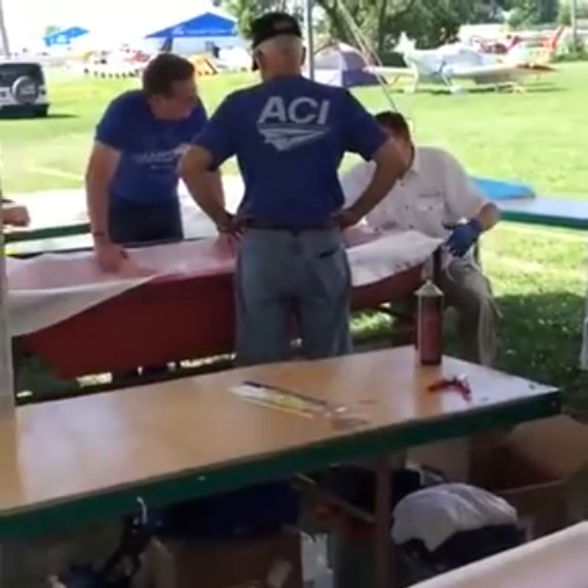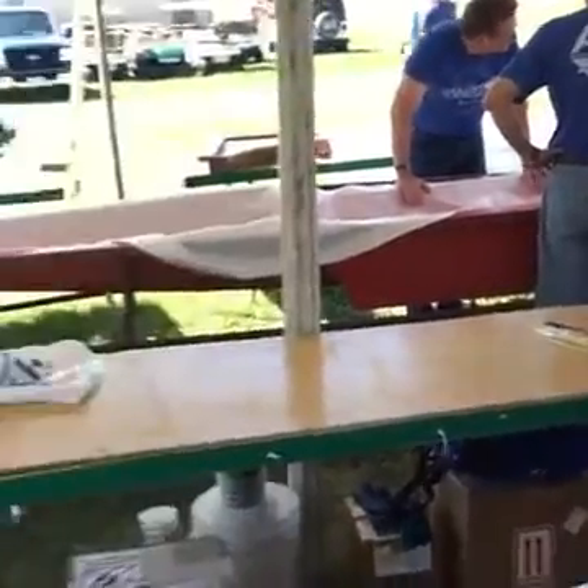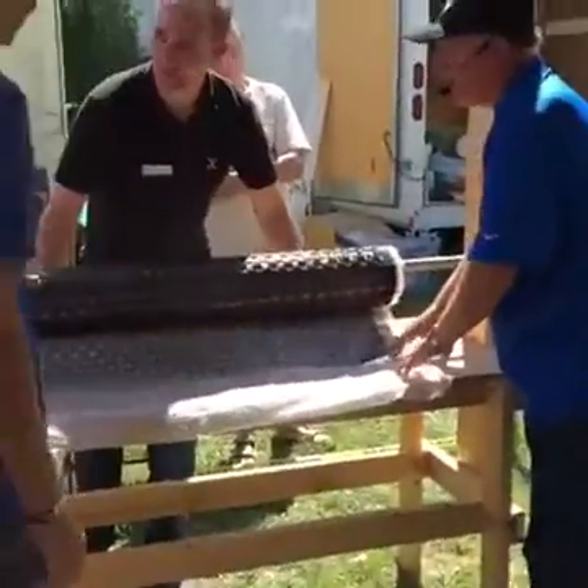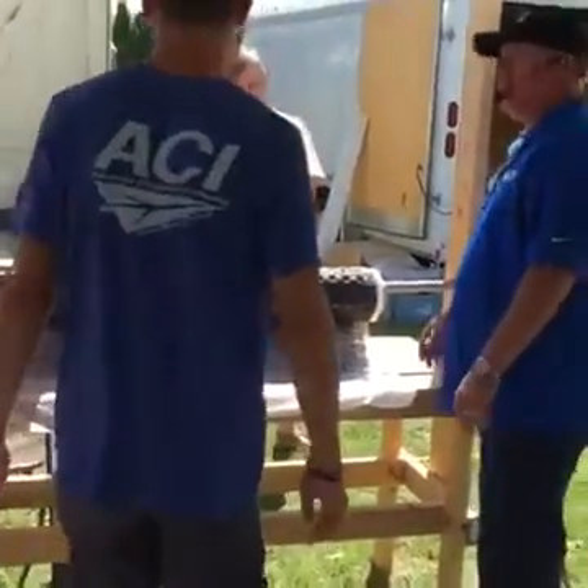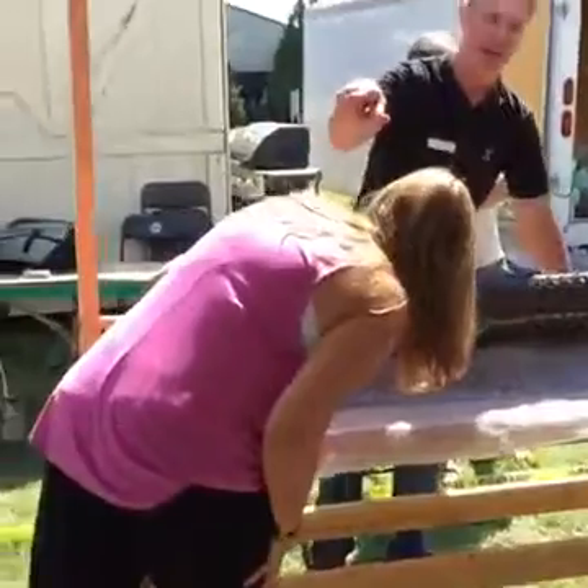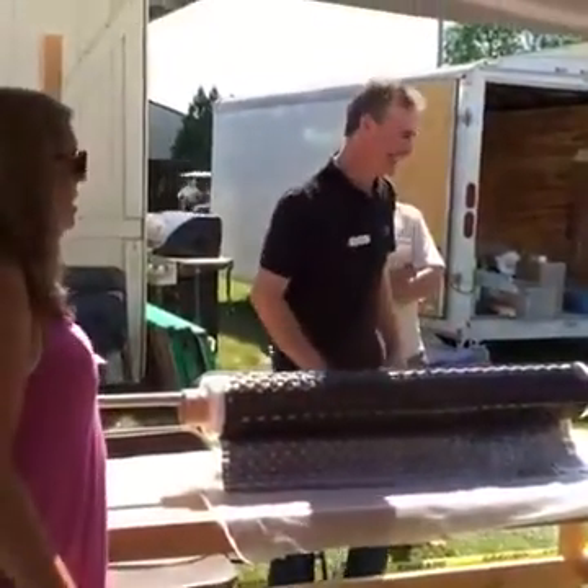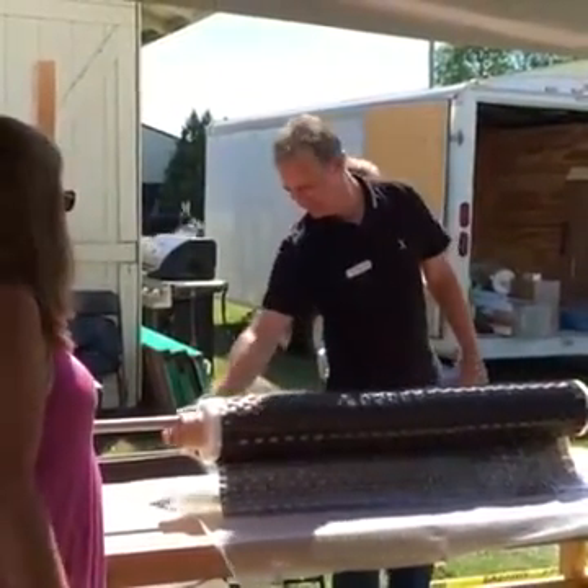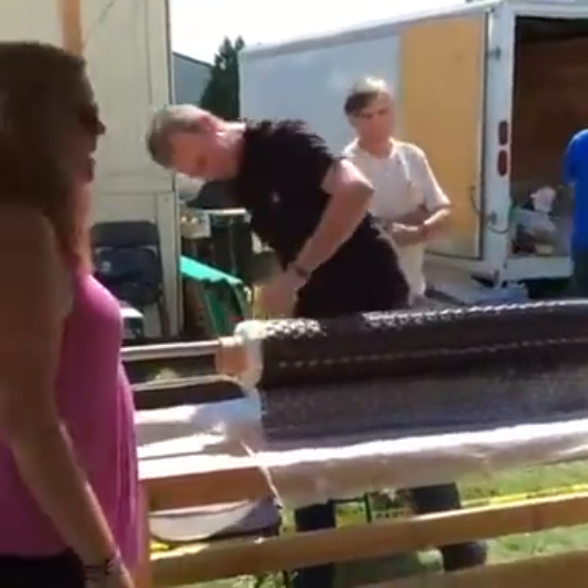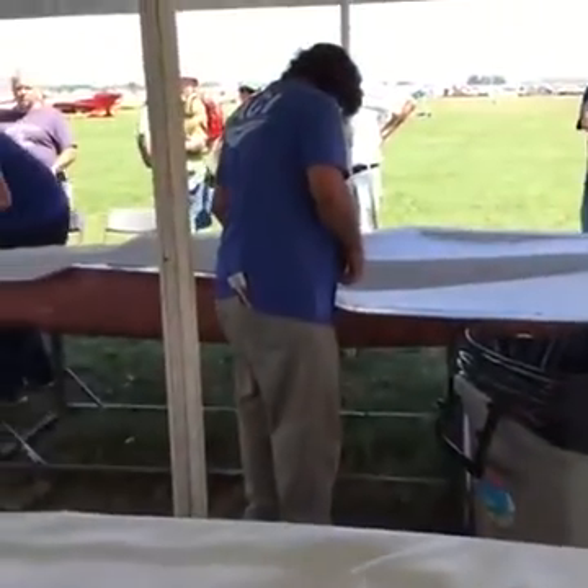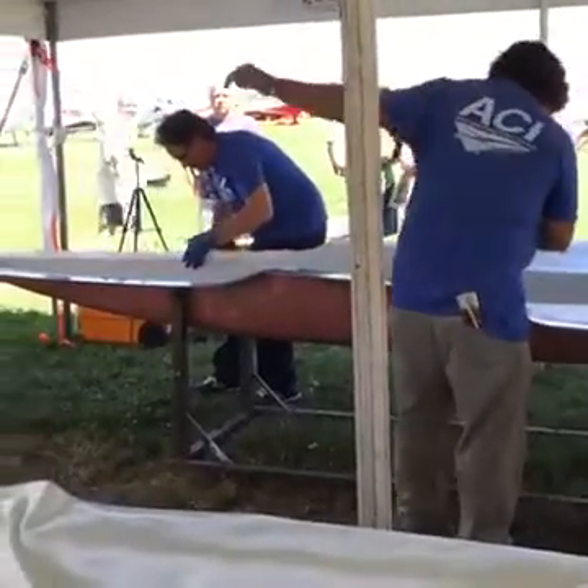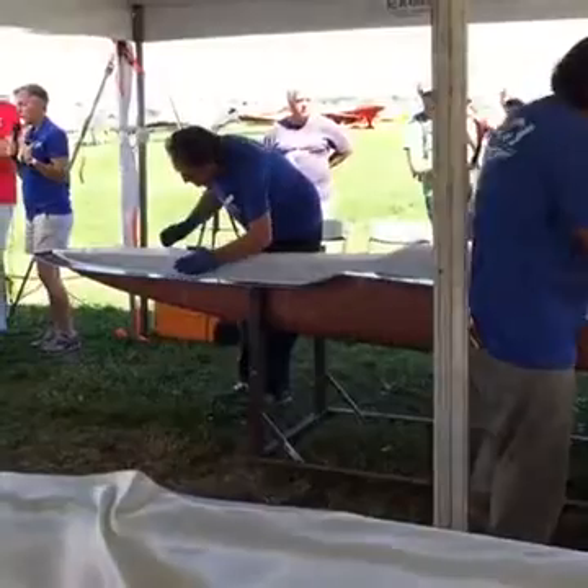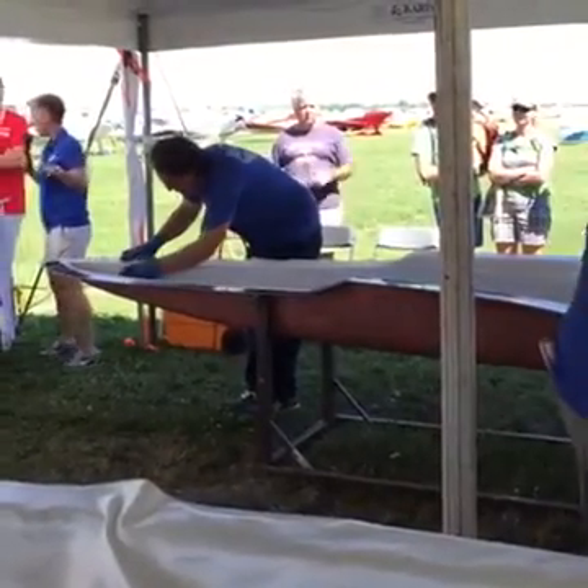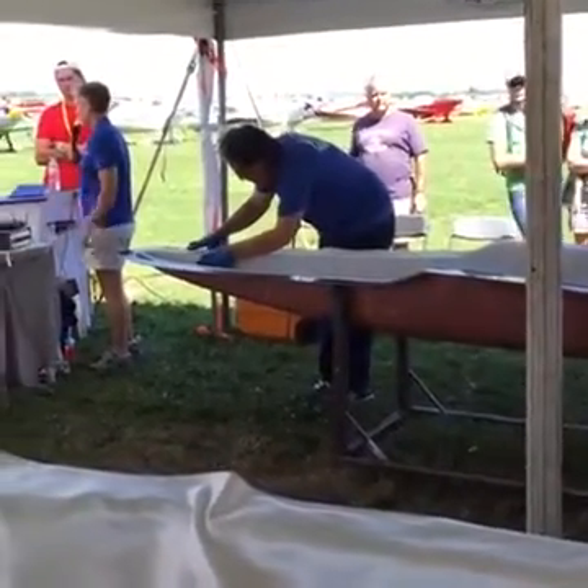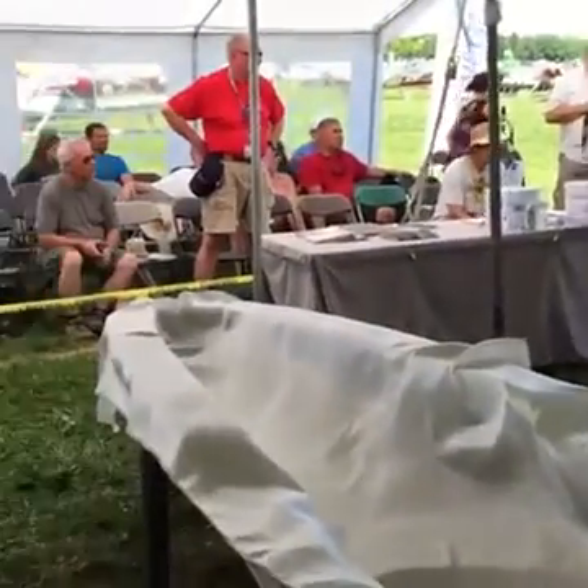With the commingled? Okay, so the question was, with the commingled, is it just commingled in strands or is it twisted? It's actually needled. The process is infinitely one shot. They're not twisting and they're not flat. When you look at this, which would still be considered kind of a commingled, that would be flat, but straight. So that's the way that TechStream does theirs. When we do it by the yarn, if we gave them that yarn, commingled with carbon and Innegra, they wouldn't be able to spread those two. So it gets pretty intimately blended.